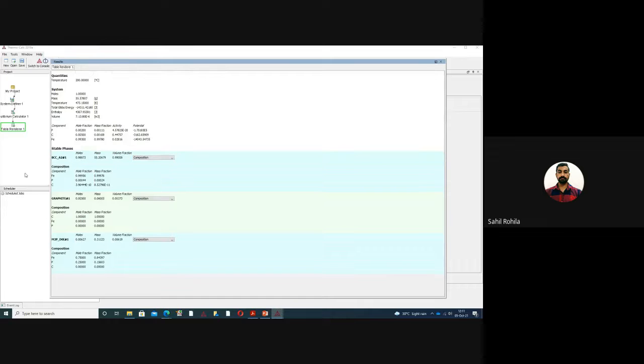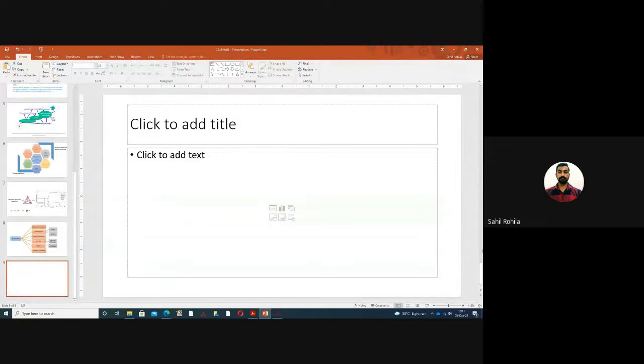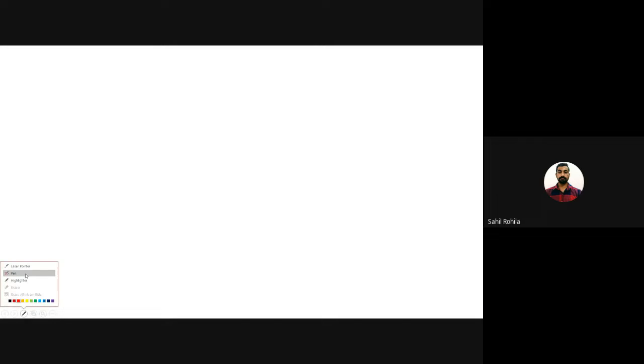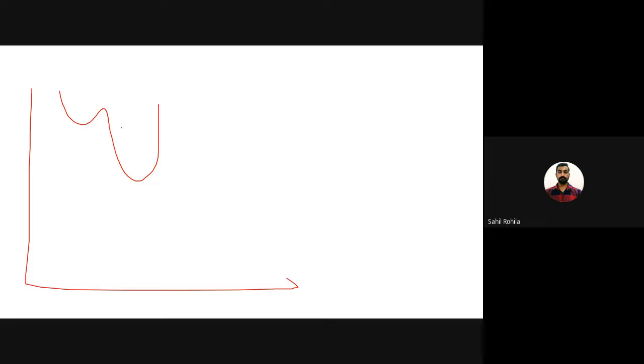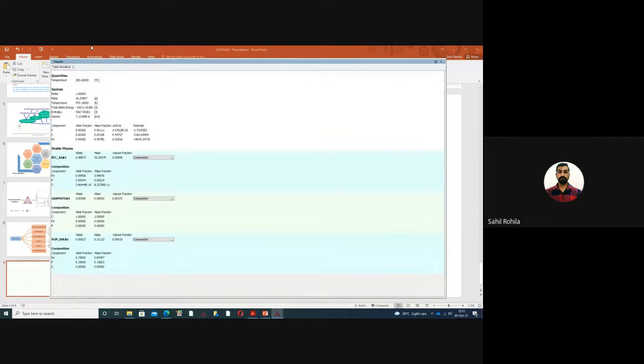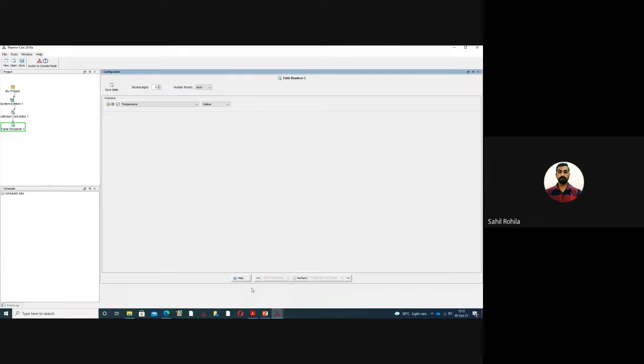So the main thing is that it is doing global minimization. So this is the metastable equilibrium. Cementite is usually the metastable equilibrium, and graphite is the stable equilibrium. So it is giving the global minimization. There will be many types of alloys where the complete equilibrium will not be reached. In steels, cementite will transform to graphite, but the activation energy is so high that it will not reach graphite, but it is giving us slightly different information.